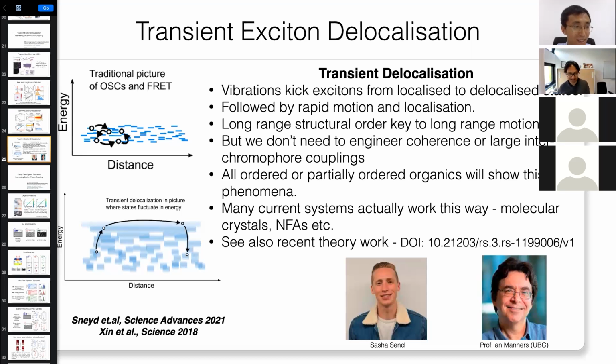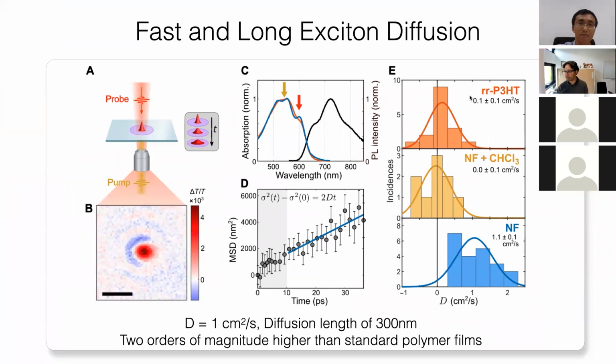My second question is that when you study the exciton transport, is there any big differences between the organic small molecules and polymers, such as P3HT? So it depends on essentially how this process works. I showed you over here, for instance, if you have normal P3HT films, the exciton transport is very poor because the films are very disordered. If you can make ordered films with these polymers, then you can have very nice transport lengths. So essentially, it's not the base molecule, but how they are ordered that matters. You can take the same P3HT polymers and make very ordered films out of them and get very nice transport, or you can have a very disordered film and get very bad transport.